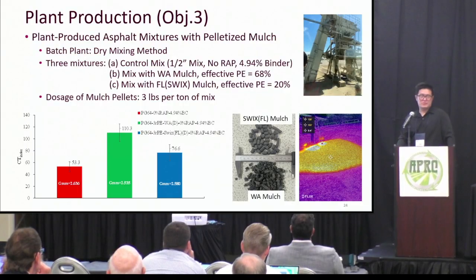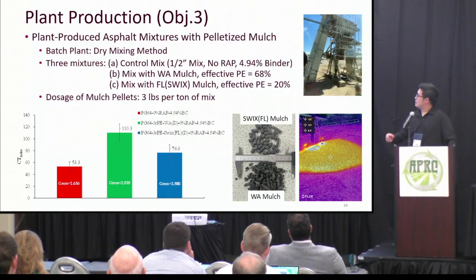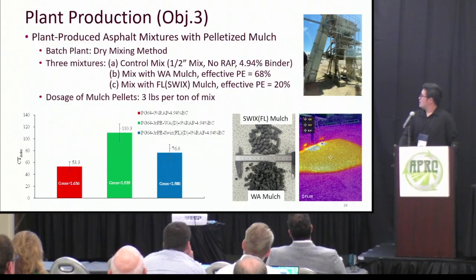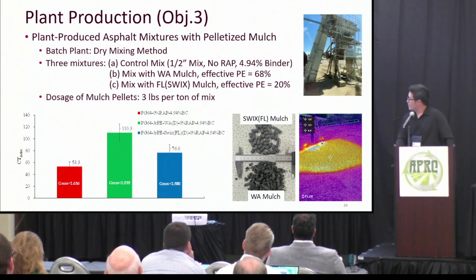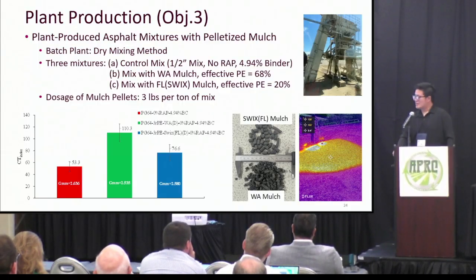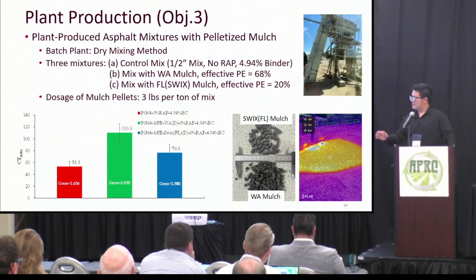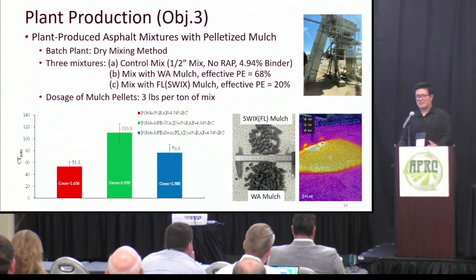And also we scaled up to produce plant asphalt mixtures for 3 mixtures. One is a control mixture without plastic, and one is mixed with Washington mulch, where the effective PE content is 68%, and one is from Florida, and the mulch effective PE content is 20%. So now we just ran the anti-cracking test. It shows the mixtures with plastic have better anti-cracking property than the control mix. Next we will run the rutting test, fatigue test, and moisture damage test.